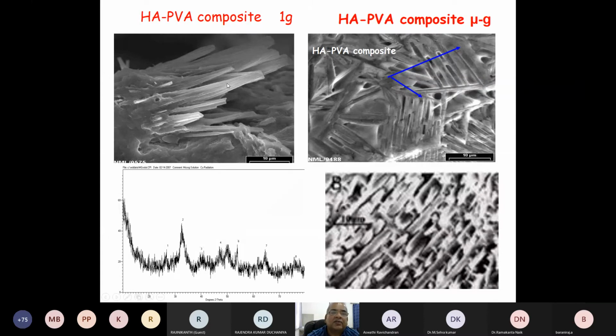So here this first photograph shows the hydroxyapatite rods synthesized in our lab under the same condition as under 1G, for the same chemical concentration and so on as for the space. And this is the one we developed in space. You can see highly oriented, long range, parallel hydroxyapatite rods. Here it's a random bundle. And when we looked at the microstructure, like the tooth enamel, it is very similar to what we have got under microgravity. And from the X-ray diffraction, we confirm that we are dealing with hydroxyapatite and nothing else.